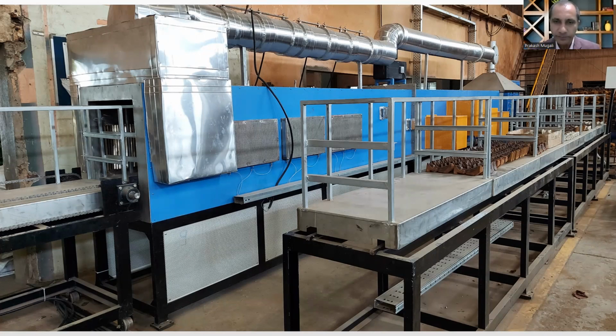Okay, great. What should be the minimum temperature required, and what should be the timing for this drying you recommend? Here the temperatures are around 140 for the heated air. Anywhere from about 120 to 150, you can vary the temperature. You can set the temperature, it is in your hand. We recommend the heated air temperature to be kept at 120 to 140. And the microwave is power controlled. You can set the power, and the temperature will be limited in that range, 120 to 140.